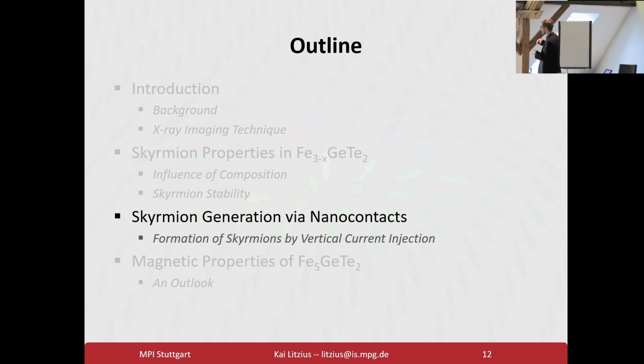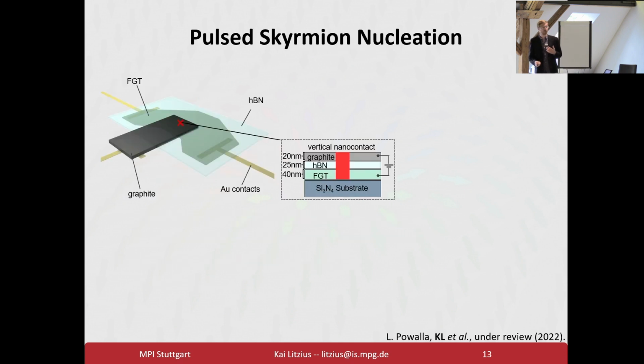Anyway, now that we know we have skyrmions, we can stabilize them, and we know where they come from, let's talk about the generation in a nanocontact system. For this, we need to first fabricate a device. In this case, we can generate it by patterning contacts on top of, in our case, a membrane to look through them. Then we put a flake on top. This is this greenish area. We cap the flake with an insulating material, in our case hexagonal boron nitride. And this layer here is a graphite sheet, which we use to contact on top. So if you look from the side, we have a silicon nitride substrate, we've got the FGT, we've got an insulating layer, and we have the graphite that just couples it into the next contact.